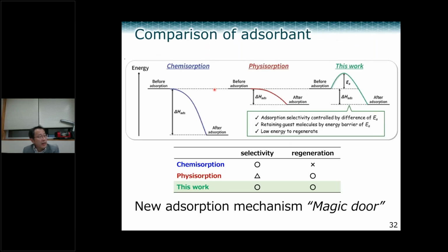Okay, this slide summarizes some sorption depending on the sorption type. In the chemisorption case, you can strongly trap the CO2, so you can expect very large stabilization energy. In the physisorption case, you cannot expect so large a stabilization energy. However, for regeneration, you need only a small energy. In our MOF case, the energy scheme is like this. First you need a little bit of activation energy. However, you can stabilize CO2 with this amount. Then for regeneration, you don't need this energy.